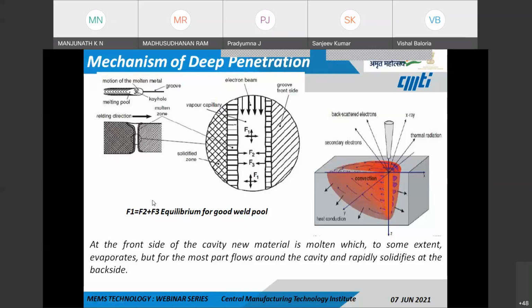Now at the front side of the cavity, a new material is molten, which to some extent evaporates, but for the most part flows around the cavity and rapidly solidifies at the backside. So we see here that once the electron beam is passing through, the melt pool is flowing back towards the melt pool and then solidifying. So that is the reason we see these bead formations.